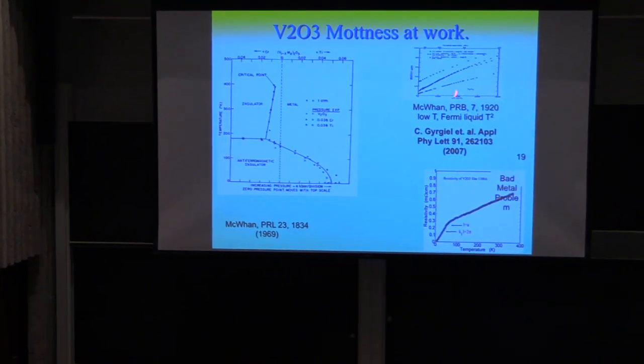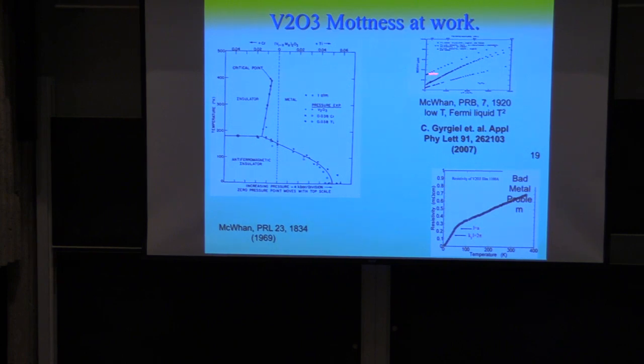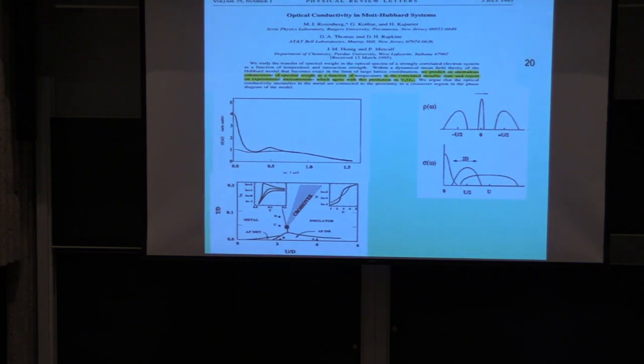The resistivity at very low temperatures is like the standard model, has T square resistivity. But if you look at it on a much broader scale, it's also the type of bad metal where the resistivity is very, very large. So that was one of the first motivations for developing the dynamical mean field theory. It was a very, very old problem. And what we were able to sort of show is